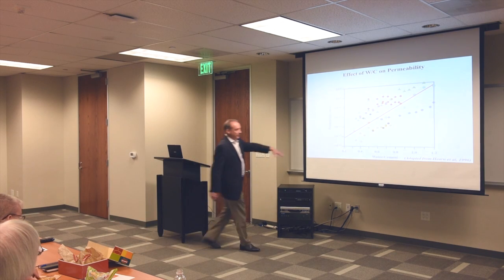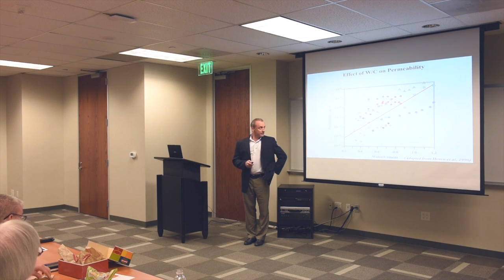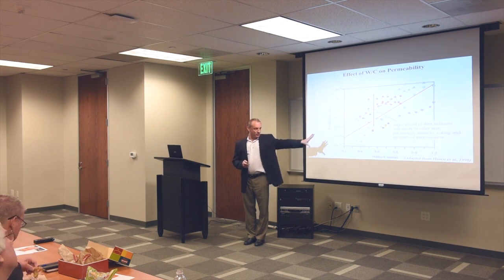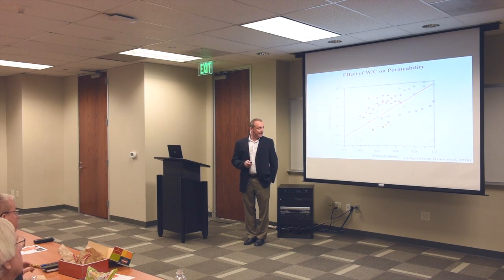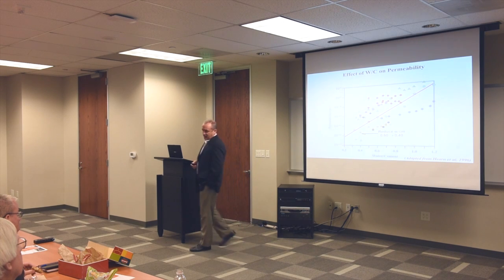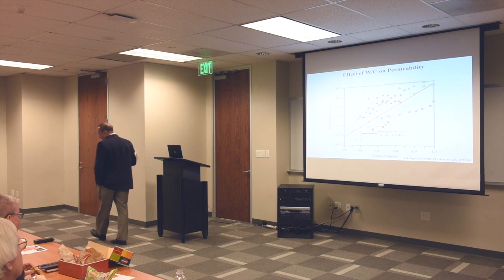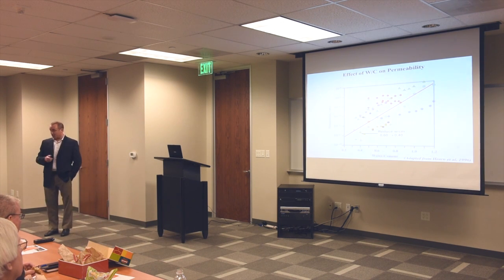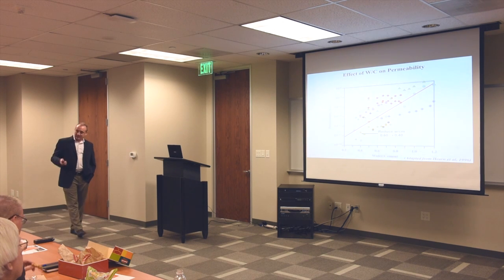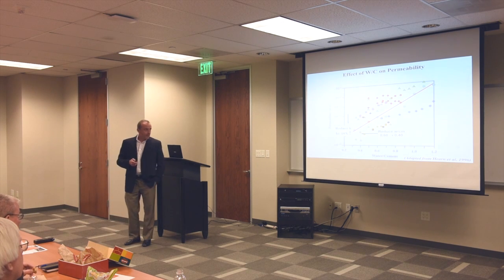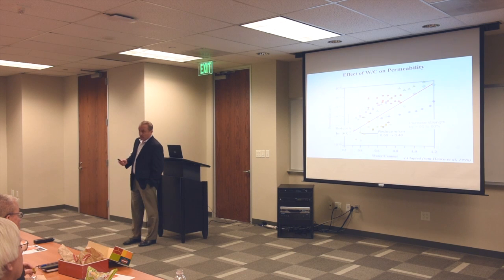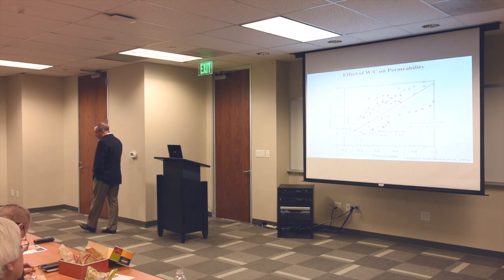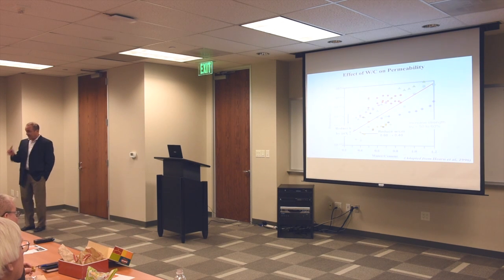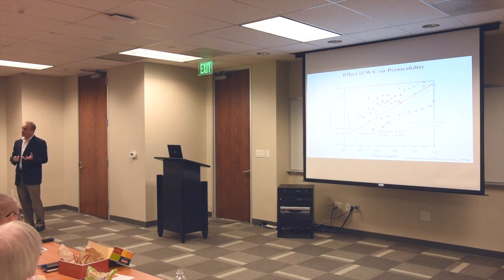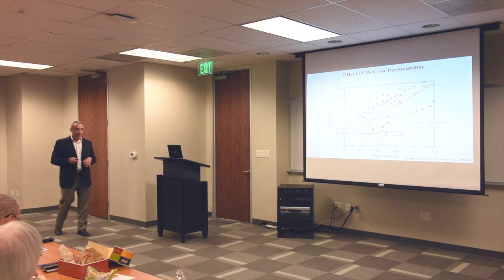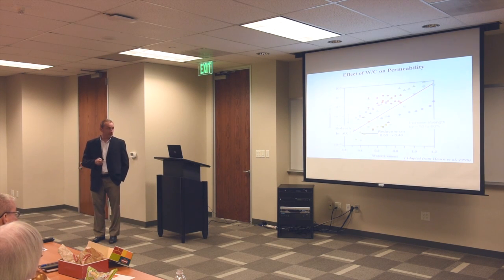There's a lot of different data from different sources here, so it's not a perfectly straight line by any means. But what you'll see is if you lower the water to cement ratio—our standard litmus or benchmark for concrete strength and durability—from 0.6 to 0.4, we'll increase the strength by about 50%, but we'll reduce the permeability by a factor of 10 or more. So the water to cement ratio, although it controls strength, is the key to reducing the ingress of water by keeping that ratio down. It produces a less porous structure, and that's what we're trying to shoot for in an aggressive environment.